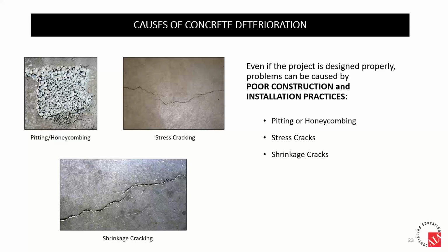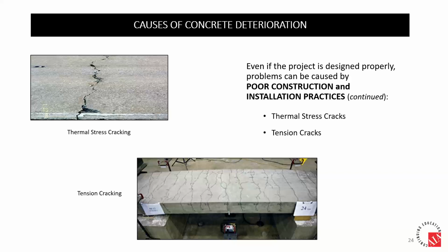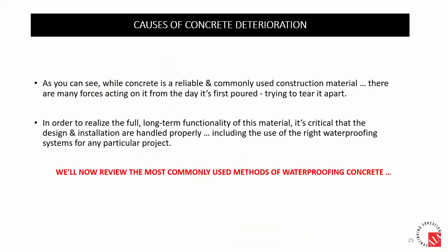Some other things that can happen are more relative to the installation or the construction. For example, too much water during curing, and you see the picture of pitting and honeycombing, and then cracks on the surface. This is again relative to construction and installation. Not being able to move properly causes cracking, and too much or too little tension can cause cracking. So concrete, again, is very reliable. It's very commonly used, but it has a lot of strikes against it, trying to deteriorate it unless we select the proper way to protect it.